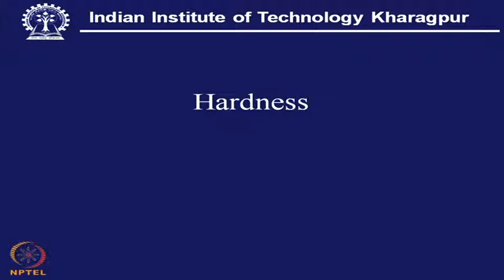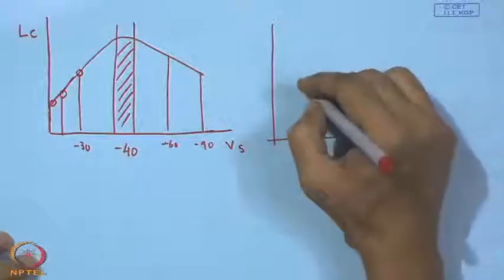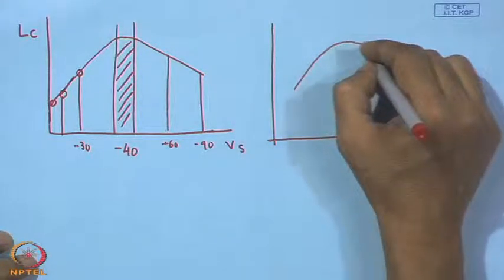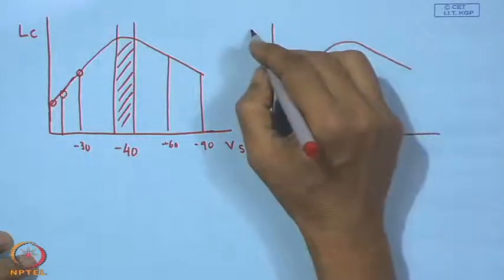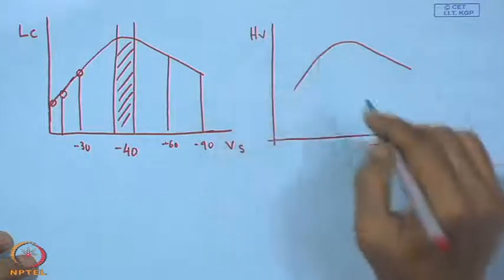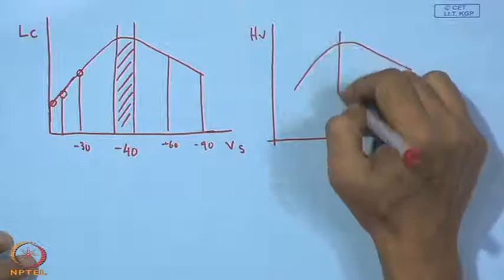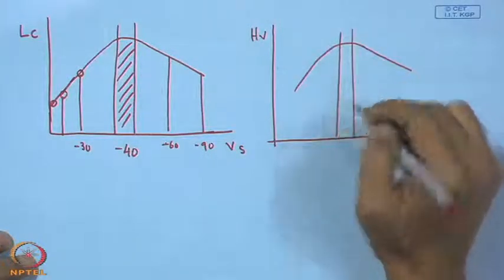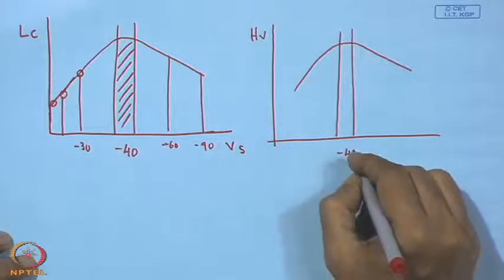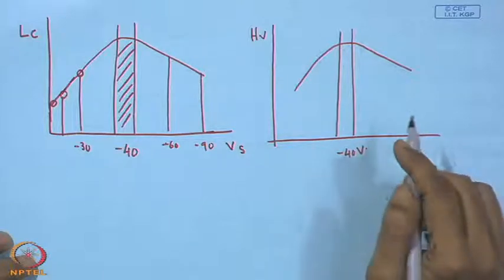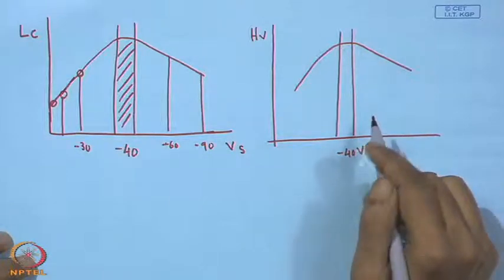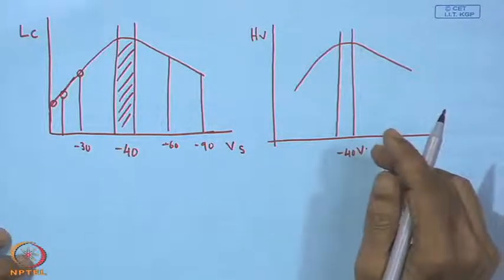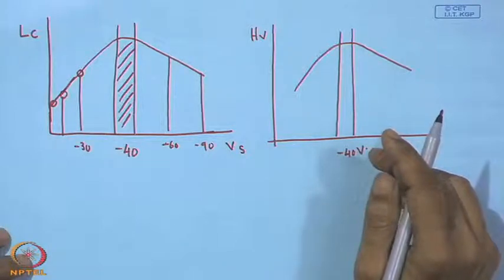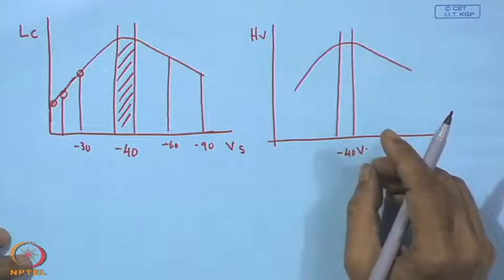Hardness. Now, this hardness can also have a curve like this with substrate bias, and here also a zone we may come across around minus 40, and this is where we have densification of the coating, closing all the pores and voids.